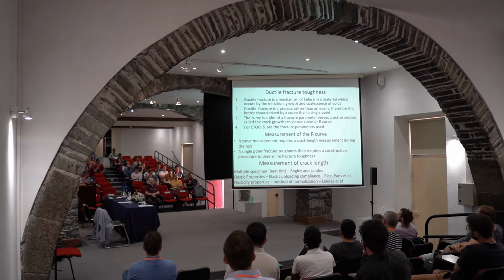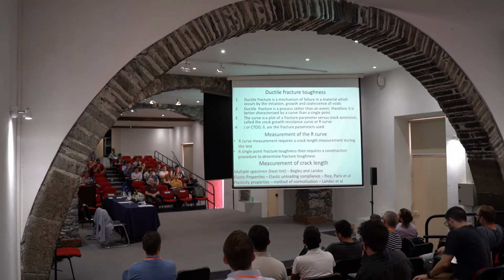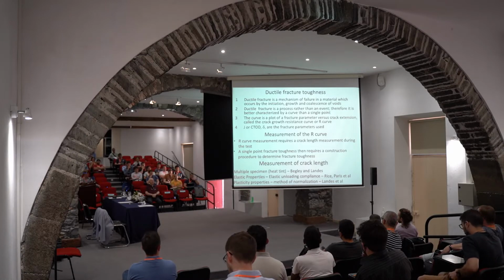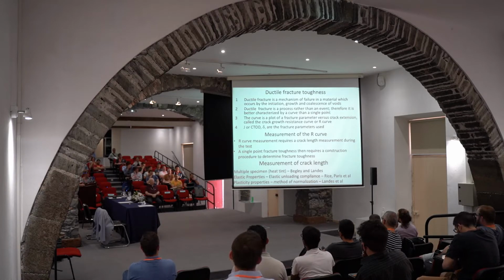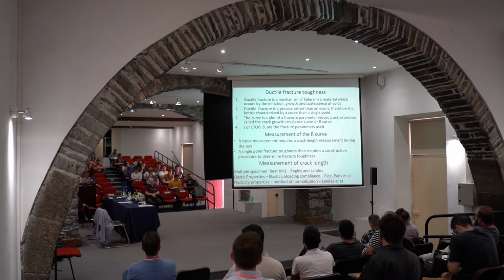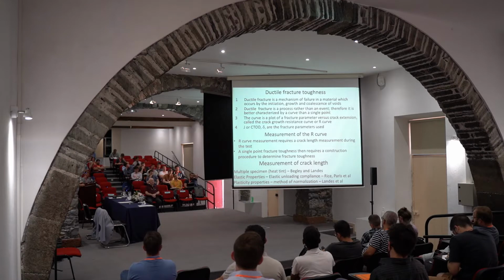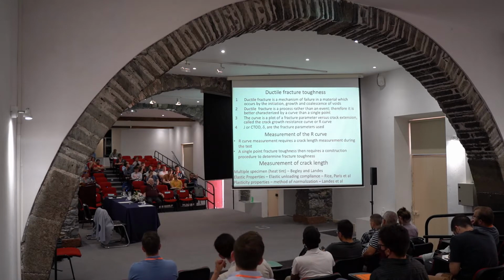So to evaluate this ductile fracture toughness, we also need to measure the so-called resistance curve. To do so, because this is now elastic-plastic behavior, it is not just an event, it is a series of events, starting with initiation of crack and then propagation of crack. To some point it is stable propagation and then it becomes unstable. So this is why we need the whole curve, and this is what was also introduced in these years that were already mentioned.